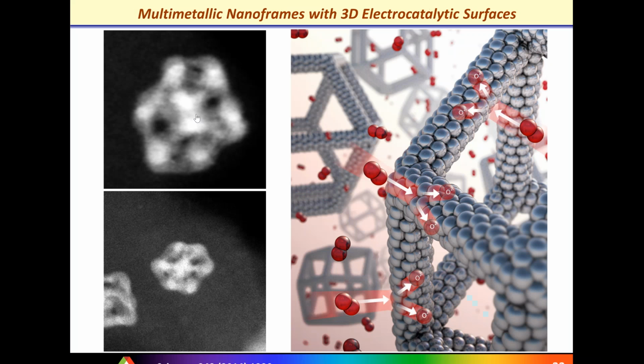And for the first time, actually, one can see this type of three-dimensional accessibility and, in other words, extremely high utilization of platinum. So for the first time, there was no buried platinum inside of a solid particle, just an open frame structure, which allowed, again, extremely high utilization of platinum. Here you can see those short 3-dimensional movies that are confirming this open frame structure.